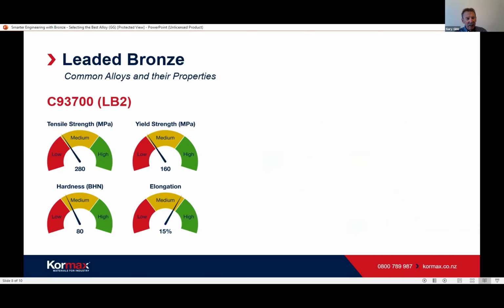So then we have a category of leaded bronzes. These are super high leaded. They have tin as well, about 7 to 10% tin, but they also have lead from about 8% up to 25%. Because of that high lead content, they're beginning to fall out of favour with the environmentalists. Lead is a toxin in the environment, so they're trying to move away from these sorts of alloys. In fact, the European standard for alloys now is 0.1% lead maximum, so these are a fair way out of it at 25%. But they're good for heavy-duty, larger-type bushes,